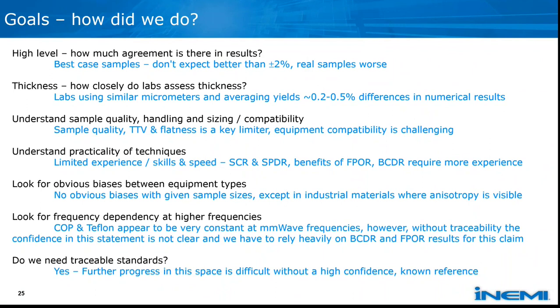In looking for frequency dependence, we didn't see any sharp COP or Teflon frequency dependence, which I think was expected. However, without traceability, we don't have a lot of confidence in this statement as to how flat this is exactly, and we had to rely heavily on BCDR and FPOR for these statements. It's possible there could be some frequency dependence that's just not obvious in the data because of the inherent spread in the different measurements. But in any case, there isn't a lot of frequency dependence, if there is any.